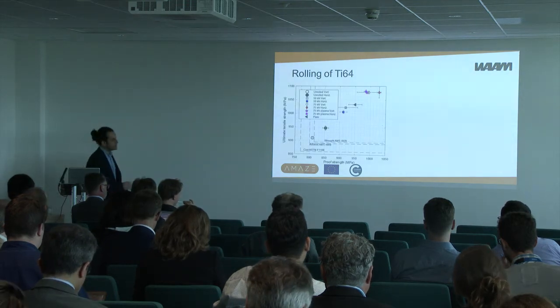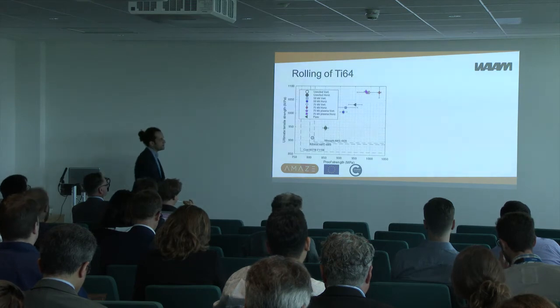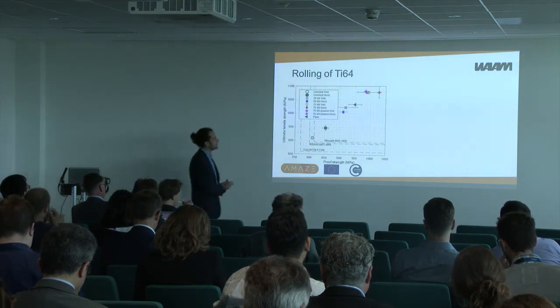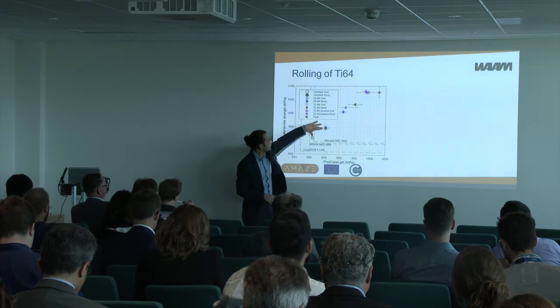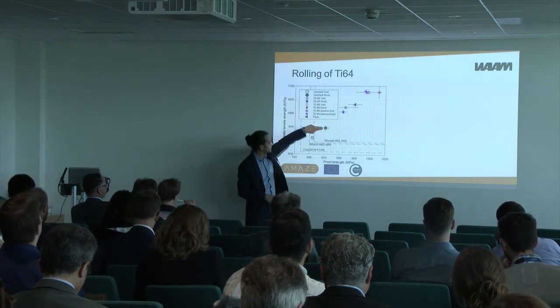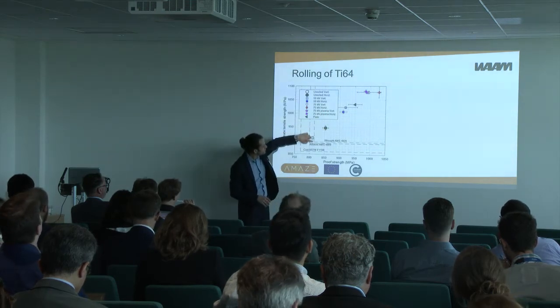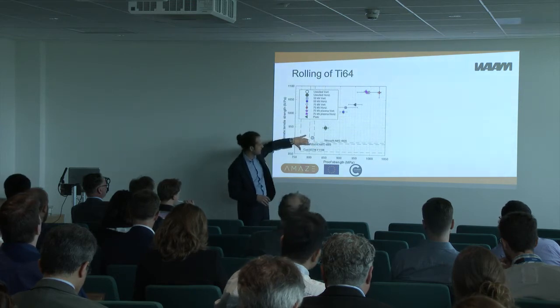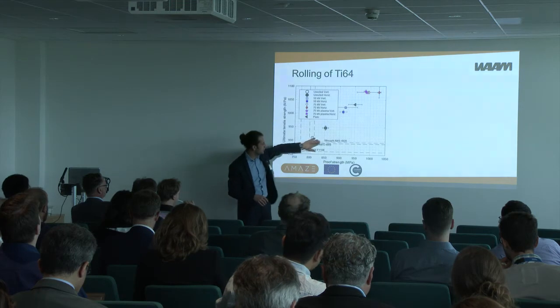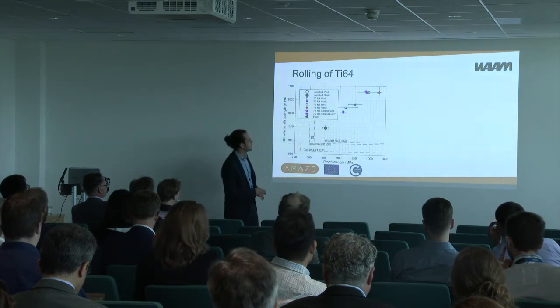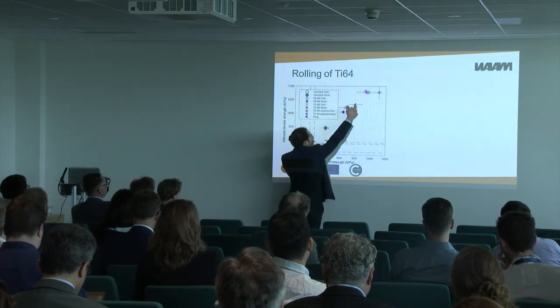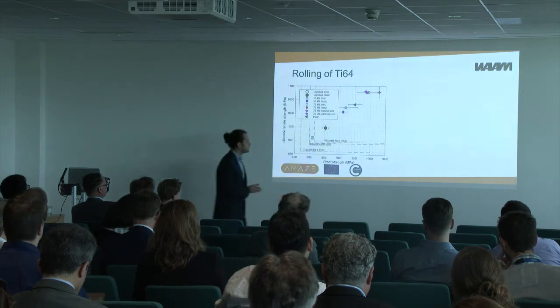So, of course, the next thing we did was checking the mechanical properties. As you can see from this case, which is the unrolled vertical and unrolled horizontal, we are almost compliant to the specification for rod products. So we are definitely above the one for additive and cast, almost good for the rod. Nevertheless, we are still far from the current performances of the rod material.